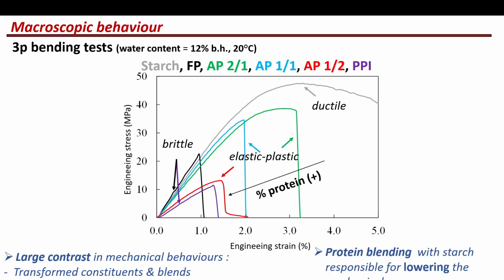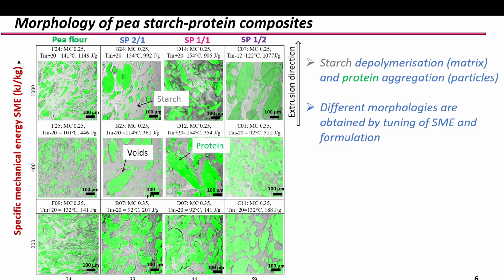At the same time, we can see clearly that the protein blending with the starch is responsible for the lower ranking of the mechanical response of the composites due to the brittleness of the protein aggregates. In order to explain these correlations, we used CLSM imaging, where you see here the starch phase appears in gray level and the protein in green color. Basically, we see the effect of the starch depolymerization as a main aspect of the matrix transformation, but also the appearance of the protein aggregates, which are more or less dependent on the extrusion process. So there are different morphologies that are obtained by only tuning the SME and the formulation.